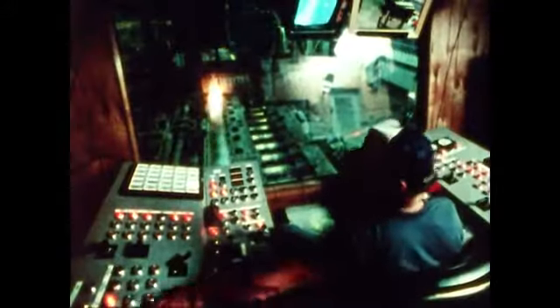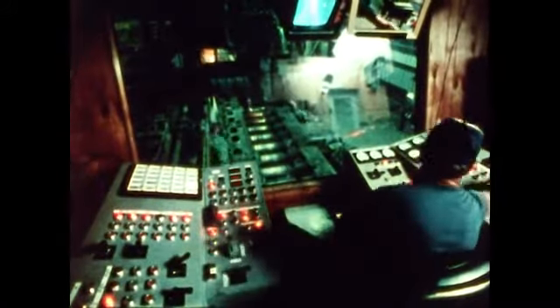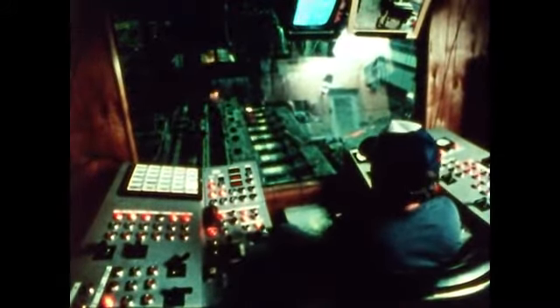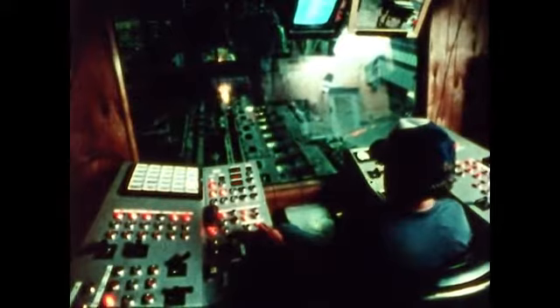Each squeeze of the mill and each pass is gentle enough so that no splits or seams occur. Through it all, the roller operator in #1 control pulpit physically manipulates the bloom and keeps a watchful eye on the monitor screen. Each pass through the mill is under direct control of the computer using preset programming. Before leaving #1 breakdown mill, the roughly shaped rail is turned on its side. It will remain in this position without turning for the rest of its travel through the hot rolling line. This eliminates the danger of twist fatigue.